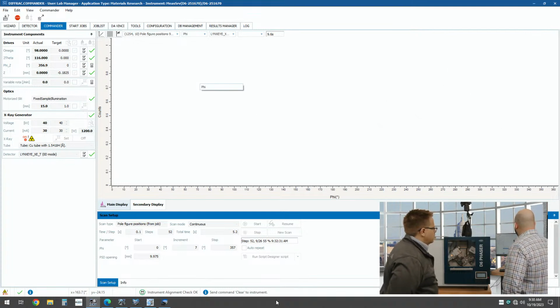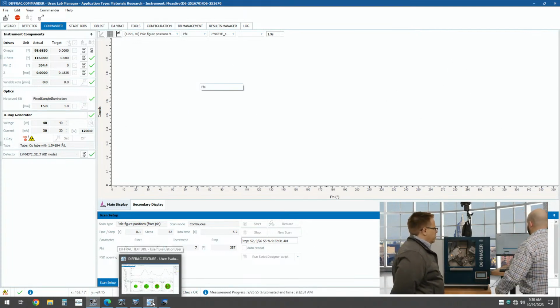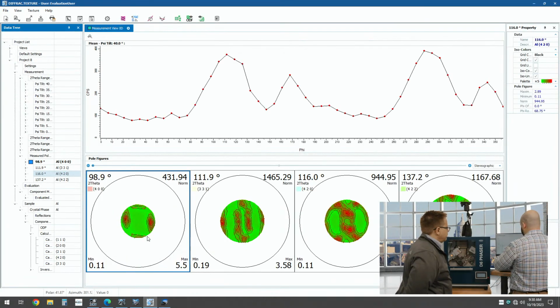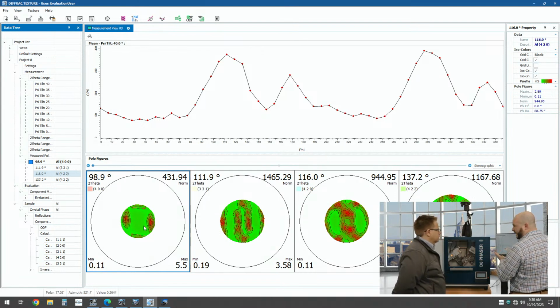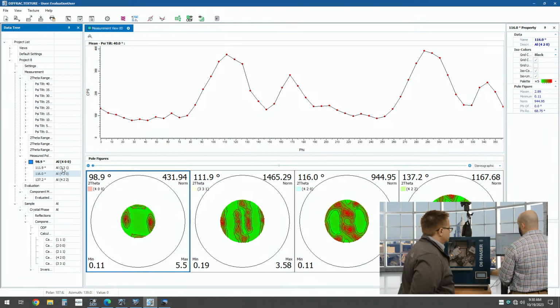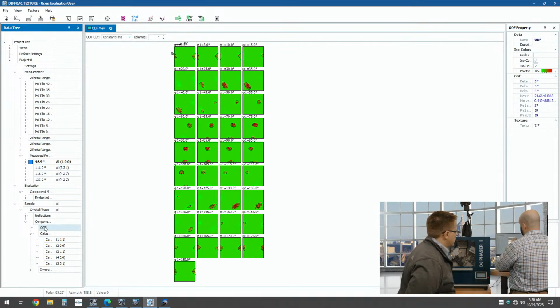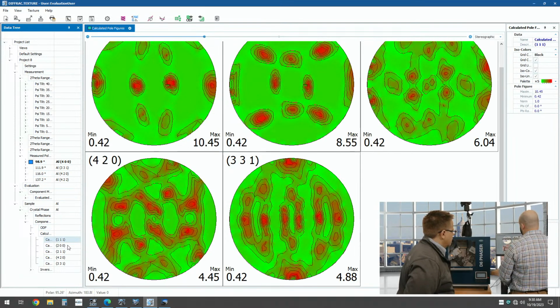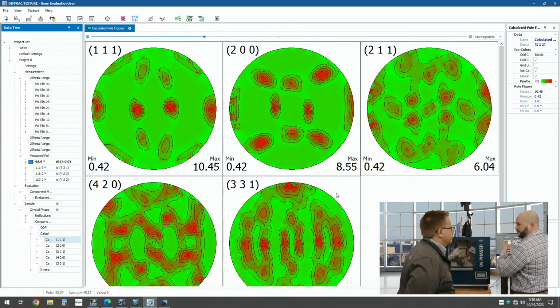So now I think you have some results, right? We do have results we can take a look at. If we turn over to the computer here, this is again the same sample, same instrument, collected a little bit longer, with multiple pole figures here. So you can see how the coverage increases as we go to higher angle, and we can use all of this information to then go in and calculate an ODF and even recalculate pole figures to fill in the range that we didn't have.